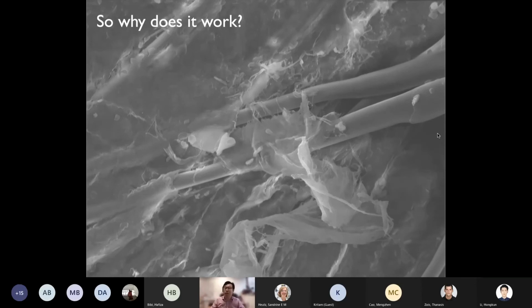Fibers are held in the nanocellulose network due to the nanocellulose hornification effect in this particular aspect, and that piece there is a dried piece of cellulose microfibers, or nanocellulose in this case, and you see the bulb of the feathers there as well.